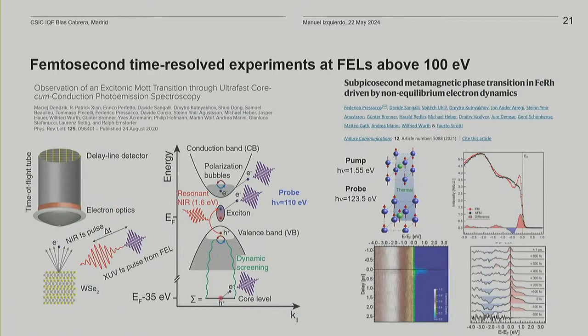And then there is also a project in China, SHINE, that is supposed to start doing experiments also next year. So some of the things that this possibility has enabled, I am going to go very briefly here. For instance, it has been used to study excitonic Mott transition in tungsten diselenide by doing a resonant excitation at 1.6 electron volts of the exciton and see how the system evolves as a function of time.